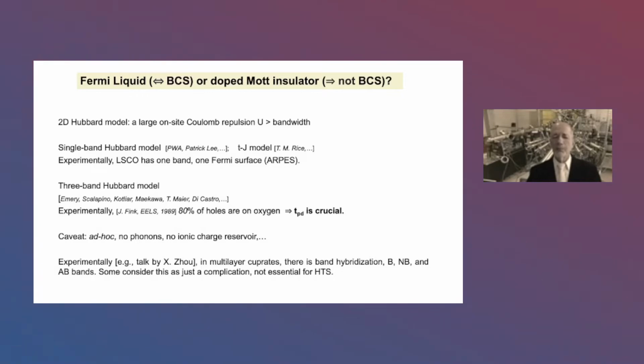experimentally, again, more than 30 years ago, beautiful experiments by Jörg Fink at Karlsruhe using electron energy loss spectroscopy showed that holes are actually not sitting on copper, they are sitting on oxygen more or less. Or at least 80% of the whole spectral weight was coming from oxygen. And that means that in this plaquette where you have copper and oxygen, there is a hopping integral matrix element, which is hopping from copper to oxygen, that is actually crucial. And that's a justification for the three-band model.